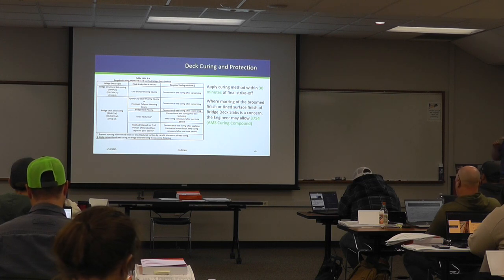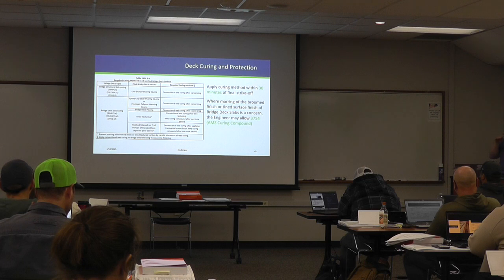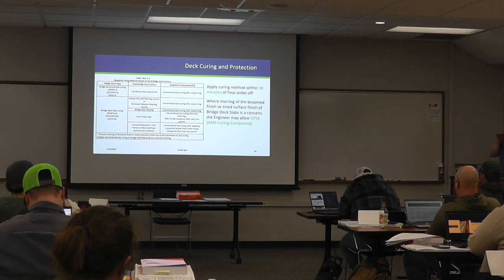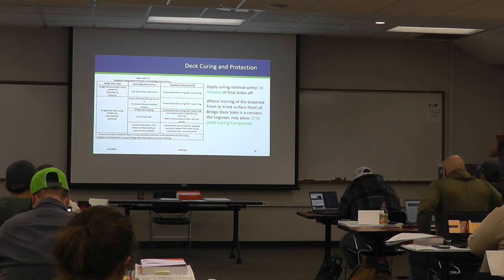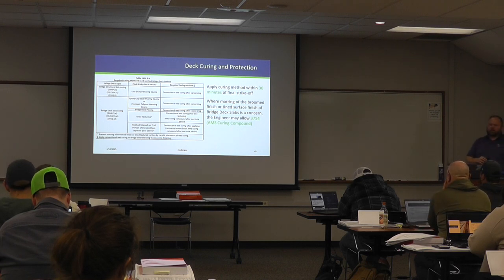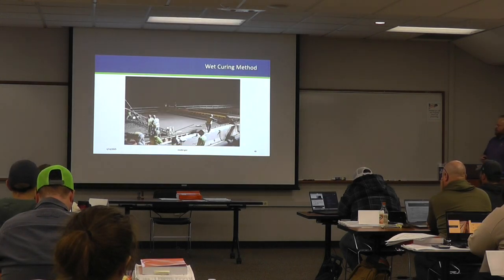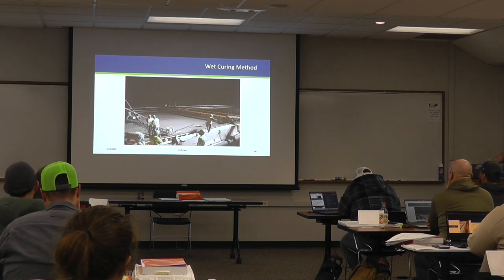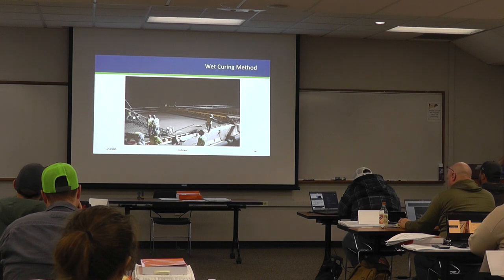And so you see in studies that the concrete that's wet cured is just slightly better in terms of strength and durability than concrete that has membrane curing compound. Now that's not to say that membrane is bad, it's just why wet curing is preferred if it's possible. Now here's an example of the wet curing method. So you've got your screed placing the concrete, the final strike off, and then you've got your work bridges on the back where they're placing the wet burlap down.